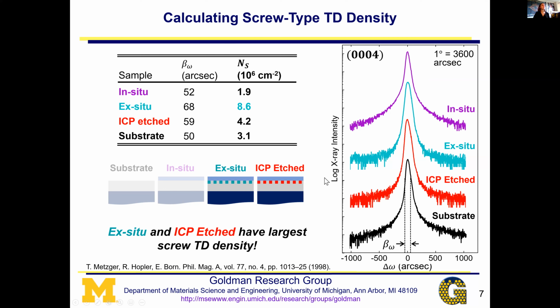And so in this case, we see that the ex situ has the largest screw type TD density, followed by the ICP etch. Both of these were the ones with interface preparation methods that were exposed to air. And we see that they have the largest screw type threading dislocation density, meaning they have the worst crystal quality in terms of screw type TDs.